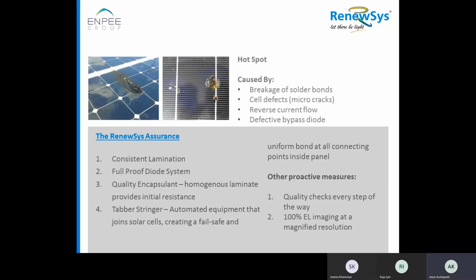The next risk is hotspot, and RenewSys is mitigating it. Hotspot is caused by breakage of solder joints, cell defects, reverse current flow, and defective bypass diodes. These are the main reasons hotspots are created. It may also happen because of non-uniform lamination. We have consistent lamination. We use a 3-step lamination process, and our Full Proof Diode System are used, with quality encapsulant, where lamination is done uniformly.